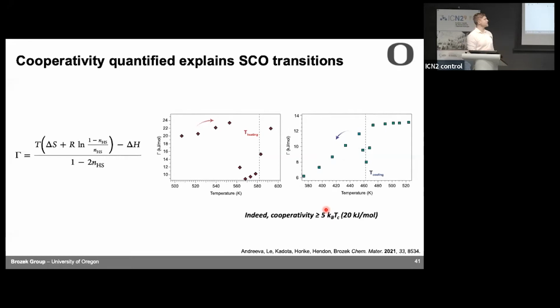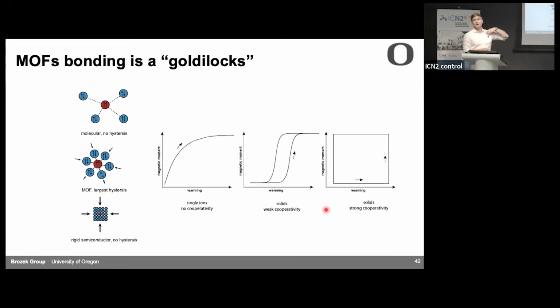Okay, but we're probably mostly chemists in the room. So what does cooperativity mean? The way that I think about it is that the bonding in a MOF is sitting in this kind of perfect in-between zone, this Goldilocks zone. In a molecular crystal, the magnetic centers aren't really talking to each other. They're very loosely connected to each other. So if one magnetic center goes high spin, the other ones don't care. It's like chemical pressure: there's very little chemical pressure on the surrounding magnetic centers. In a typical semiconductor with much denser structures and much stronger bonding, if a magnetic center goes high spin, the chemical pressure from everything else around is really, really high, and it pushes that magnetic center to be low spin again. This is why there are basically no conventional semiconductors that do spin crossover.